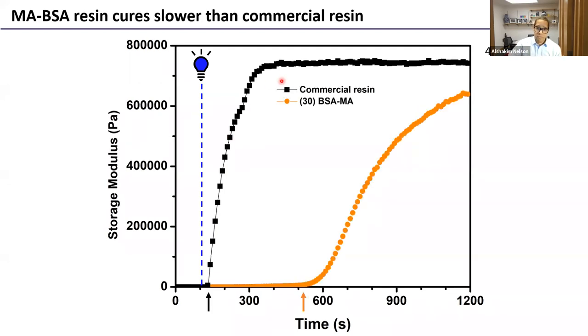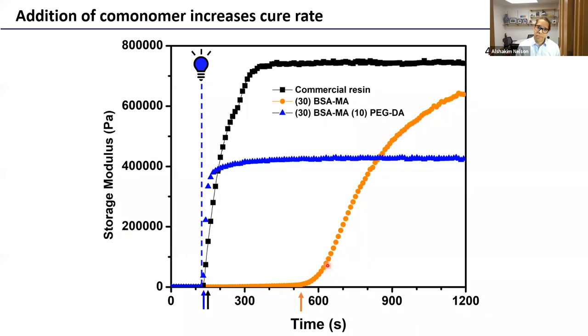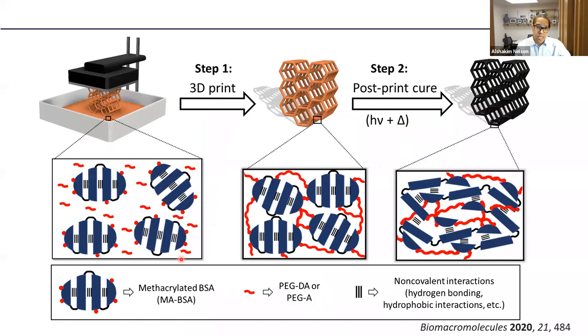Now, if we formulate with just our MABSA, without the PEG diacrylate in there, you see that the rate of photocuring is actually kind of slow, right? There's this lag period before we see a significant increase in the storage modulus or the stiffness of this material. So this is way too long, right? So this is not going to work with the printers. But what we found is that if we introduce some PEG diacrylate to the formulation, now we get a very fast response, and we're getting the photocuring speeds that are necessary for the SLA printer.